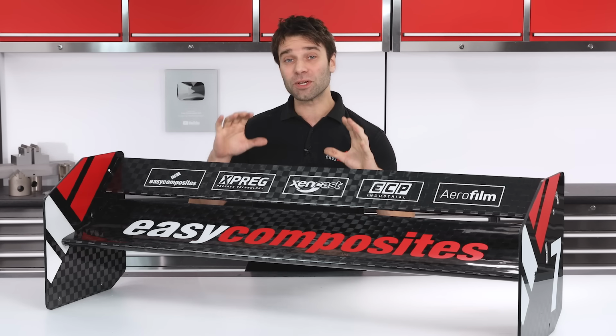At each step of the drawdown, the Mylar can be squeegeed towards the trailing edge to tighten it onto the core and remove any air and excess resin. A simple but effective tool for this is a piece of foam with some breather wrapped over it. Once you're happy that the excess resin and air have been squeegeed out and the Mylar is sitting flat, the wing can be left to cure. It should be supported in such a way that the trailing edge flows straight from the profile.